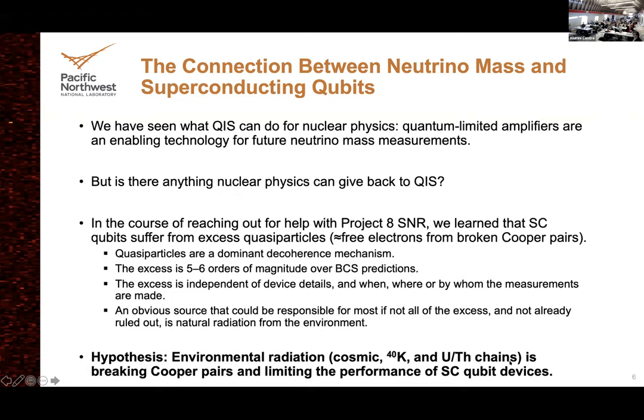It's not a small excess — it's like five to six orders of magnitude more broken Cooper pairs than what you should get from BCS theory. It should be vanishingly small, and it is not. Our hypothesis is that environmental radiation — cosmic rays and natural radioactivity in the environment, mostly potassium, uranium, and thorium — enters the device and breaks Cooper pairs.